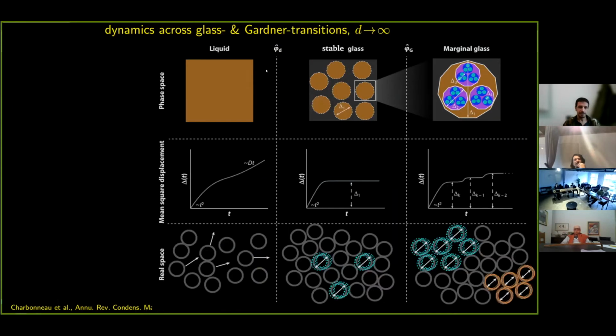And if you think about the dynamics, how are they manifested in real space? If you look at the mean square displacement of particles in the liquid state, we know how it behaves. You have a ballistic regime followed by a diffusive regime, and you have ergodicity, etc. But once you cross the glass transition packing fraction in infinite dimensions, then this partition of the configuration space into these basins implies that, of course, dynamics are going to be arrested because each system is locked into one of these basins, and then the mean square displacement just has a plateau